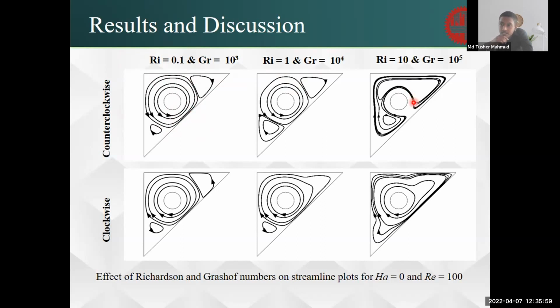So the streamlines become random. Also, as the upper surface of the wall is hot and the side wall is at a lower temperature, if we do not use any rotating cylinder, then the convection due to natural density variation was supposed to go clockwise. So if we use a counterclockwise rotation of the cylinder, it will affect the natural convection.